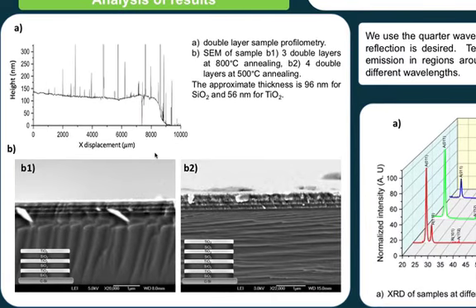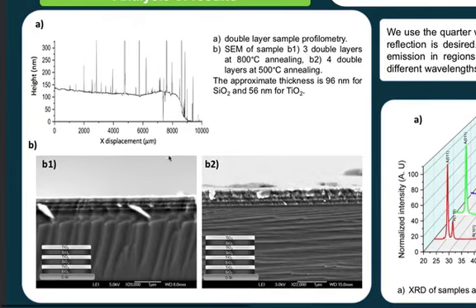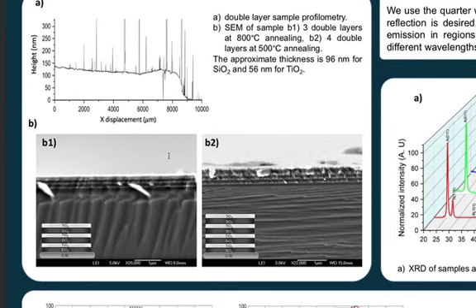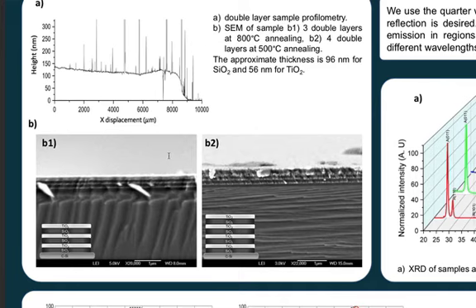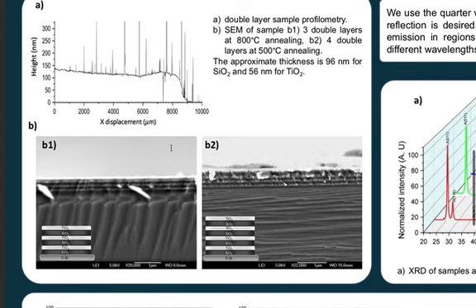What do we have? Suitable conditions were found for the growth of the materials. We found that the titanium dioxide began to deposit from 200 degrees. The deposition rate with temperature, flux, and distance from the substrate were varied to find a deposition rate of approximately 10 nanometers per 30 seconds, and similarly for the silicon dioxide.